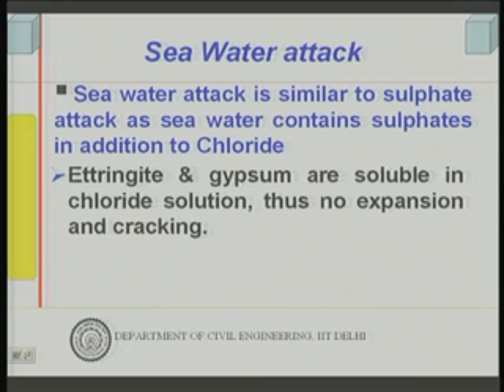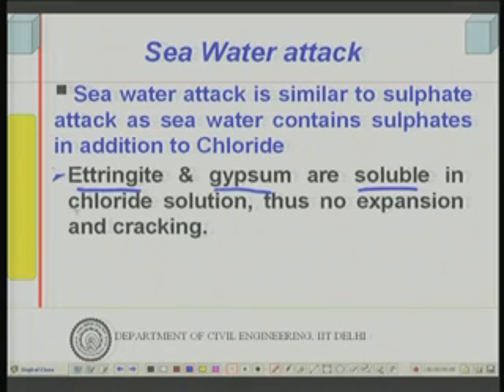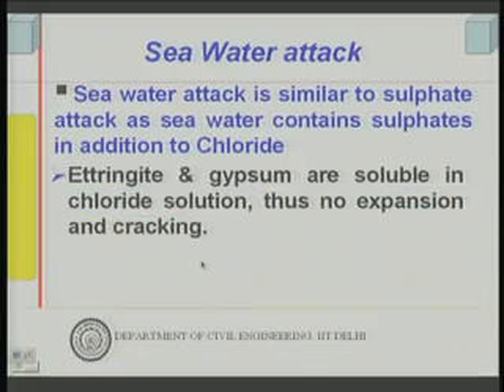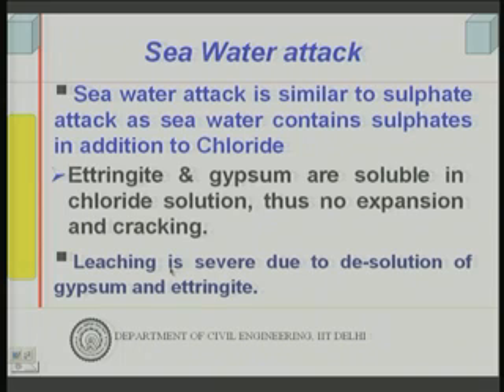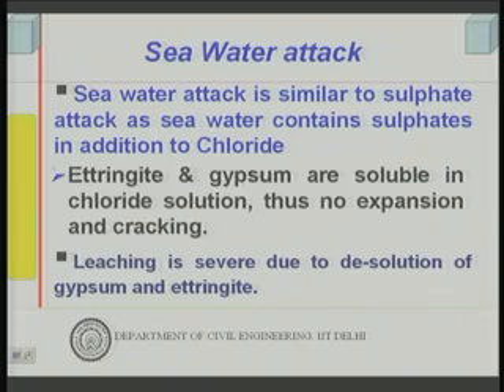The reason is ettringite and gypsum are soluble in chloride solution, thus no expansion and cracking. Since ettringite is more soluble in chloride solution, seawater, the moment it is formed, it gets dissolved. But what happens? This will result in leaching. The ettringite which is formed is dissolved, the calcium sulphate which is formed will get dissolved, and will be taken away by the seawater. So, leaching can take place and it can be severe. Dissolution of ettringite and gypsum causes severe leaching.